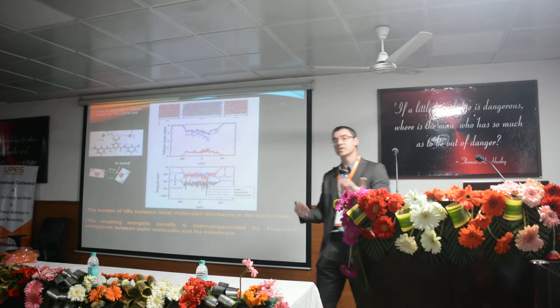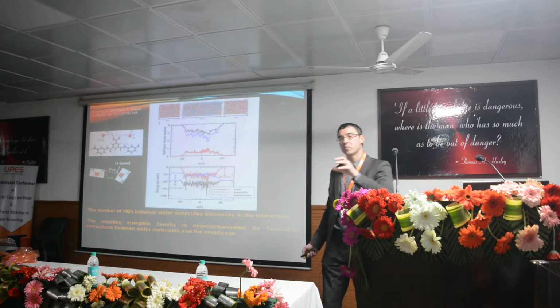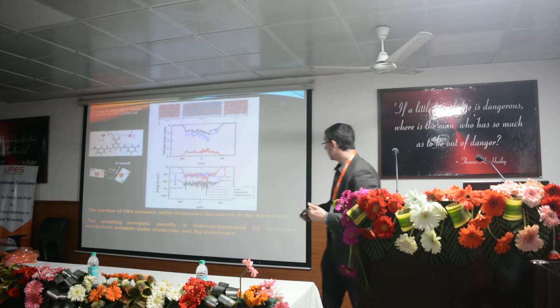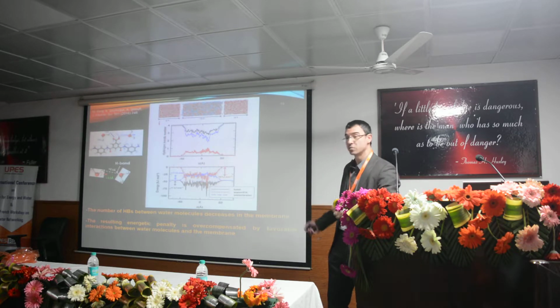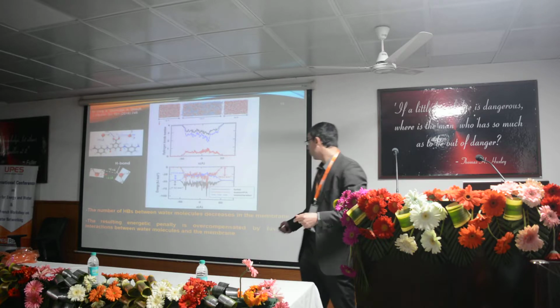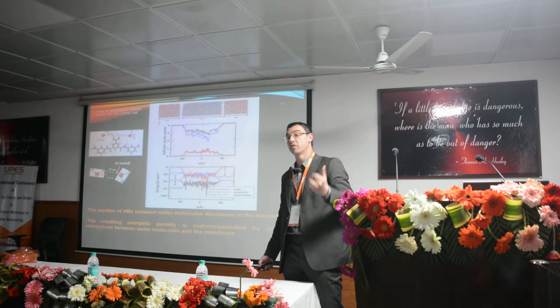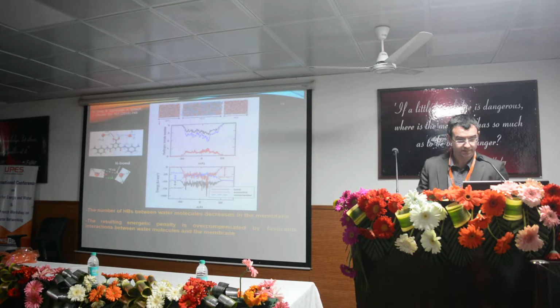But the reason why it happens is that if you compute the interaction energy between water molecules that are confined inside the polymer and the polymer itself, you obtain a rather high negative, that is attractive, interaction energy. The answer is that this very strong attractive interaction between water molecules and polyamide overcompensates the energetic penalty associated with the loss of hydrogen bonds. And that's why this kind of system can take so much water inside.